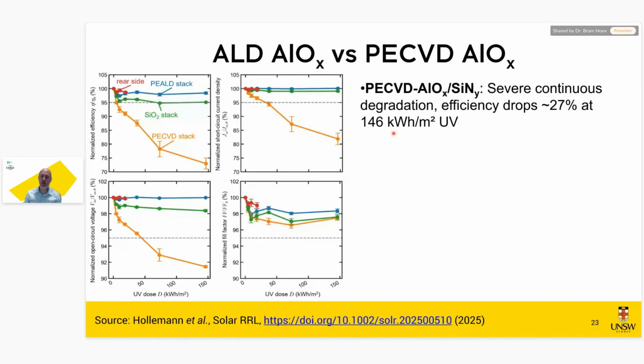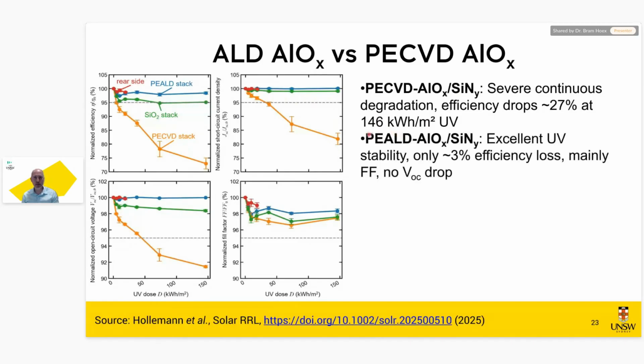testing that's typically reported. But then if we compare to plasma ALD AlOx, so the only difference is with how the thin AlOx layer is prepared. We see that that one is a lot more stable. So this is more comparable to the results we showed earlier. Our testing is a lot more extreme, so that's why we saw recombination.